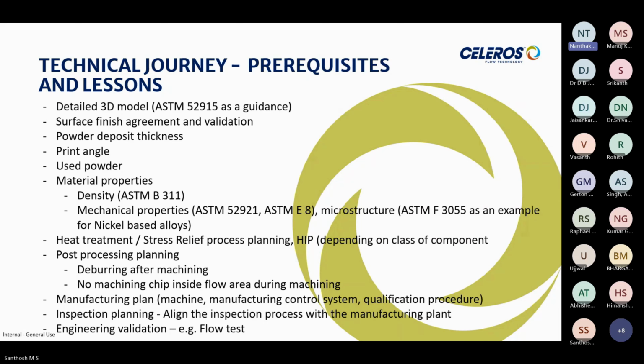We did print a dumbbell for mechanical testing along with the component. And a microstructure examination can also be done. F3055 is an example I'm citing here, which is primarily for the nickel-based alloys. For every other grade, you have a standard for that. So this is what we used.